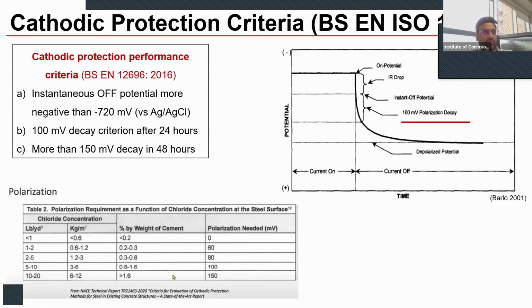If the instantaneous off potential, which is measured generally within 1 second of switching off the power supply, is more negative than minus 720 millivolt, that's one criterion. Second is if the decay is more than 100 millivolt in 24 hours, or more than 150 millivolt in 48 hours. So when the system was energized, we switch off the power, the current is switched off, we have some initial IR drop, and we reach the instantaneous off potential values.